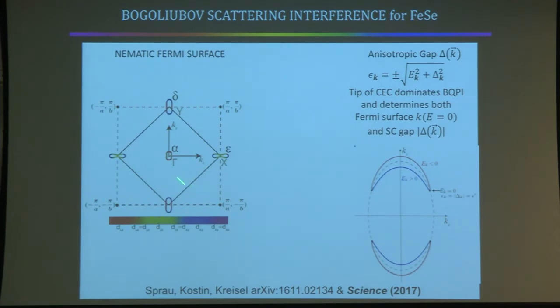Now what should we expect? If you just look at this pocket here, imagine that it has an anisotropic energy gap on it. Suppose the energy gap is very large here and very small there, just for the sake of argument. And now you go to a range of quasiparticle energy below the maximum gap. Well, you're below the gap here, so you don't see any quasiparticles. But you're above the gap over here, so you do see quasiparticles. That means these regions of momentum space have a very high density of states. You can show that mathematically.